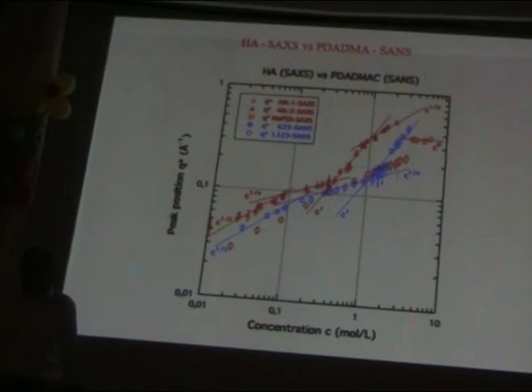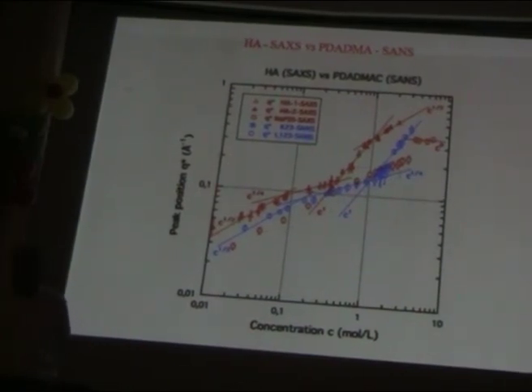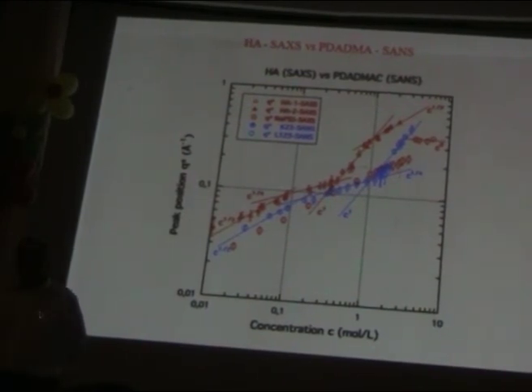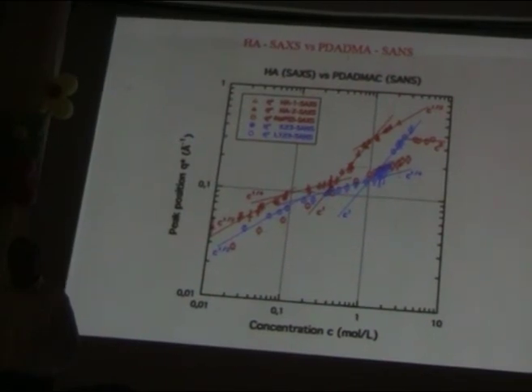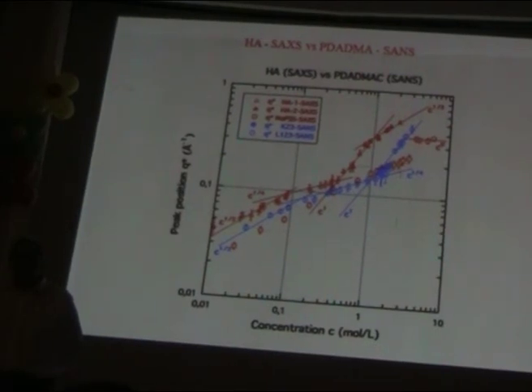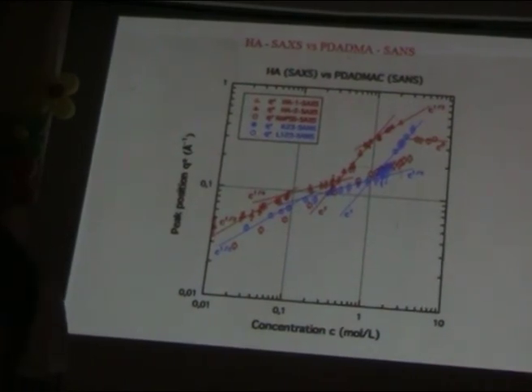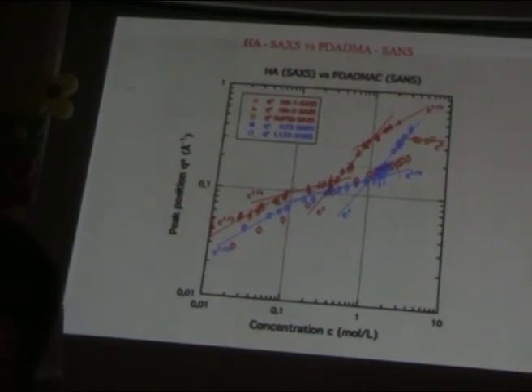As far as I understand, according to your point of view, the hydrated proton is bound better than the sodium ion to the sulfonate polyelectrolyte. Yes? But why? The ion exchange constant between these two ions on the surface of ionic surfactant micelles is close to unity. So is there really such a difference between the ionic micelle surface and polyelectrolytes?